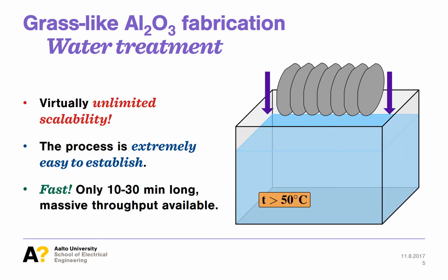The next step in formation of grass-like alumina is immersion of the ALD-grown aluminum oxide into heated water. Yes, as simple as that. Surface roughening of the amorphous aluminum oxide grown by ALD in water has been known for over a decade. But we have found that we can accelerate this process and use it to our advantage.